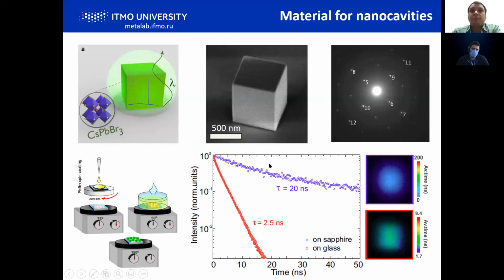As I said, we should use a material with a good cavity, with regular shape and high crystallinity. In the case of cesium lead bromide perovskite, this is the case of micro and nanocubes. Here you see a nice electron diffraction picture showing that such cubes are single crystal material, so they are perfect regarding defect properties. And we also realized that we should grow them not on amorphous glass, but on sapphire to improve their qualities.